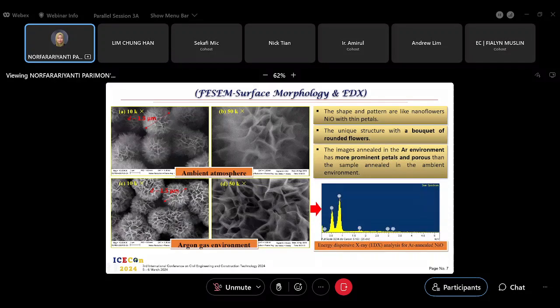From the EDX of the sample for the argon environment, we can see two well-defined peaks for nickel and oxygen, and then another two lower peaks, which are silicon and argon. Silicon is from the glass substrate, and the argon is from the annealing environment.